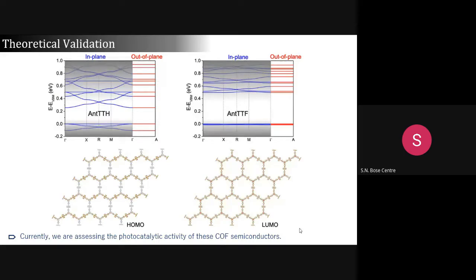So finally, we use this material for hydrogen evolution, and as we expected, this material shows very high photocatalytic activity, which we will publish soon. And we are looking into these details more, how to improve the charge carrier mobility in this kind of system, so we can get better exciton separation. First we can look into the exciton binding energy of this material.